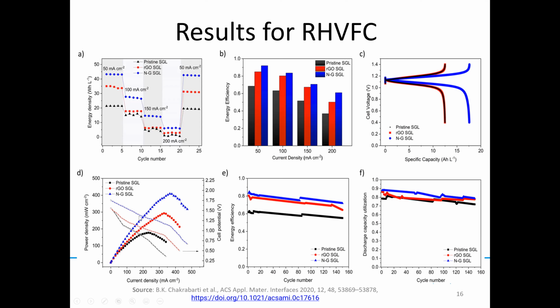Another key performance indicator is power density, which is something taken from classical PEM fuel cell studies. By doing a standard polarization curve of current density against cell voltage, we show that again, using nitrogen doped graphene, we can get a higher peak power density in comparison to standard electrodes, standard carbon paper.